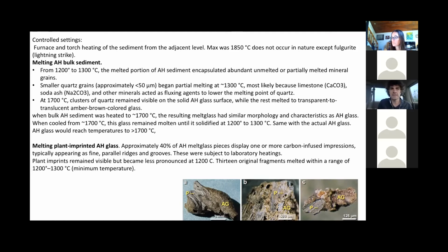We were melting this Abu Hureyra sediment, and we could see that at 1200, 1300, a melt formed, and some of the small quartz grains took part in this melt. When you have one phase, the temperature of melting is much higher than when you have more phases involved, which always lowers the temperature. That's why quartz can be introduced into the melt at around 1200, but there may also be quartz still unmelted at around 1700, which was the case here, where some quartz was still present at 1700 degrees Celsius.